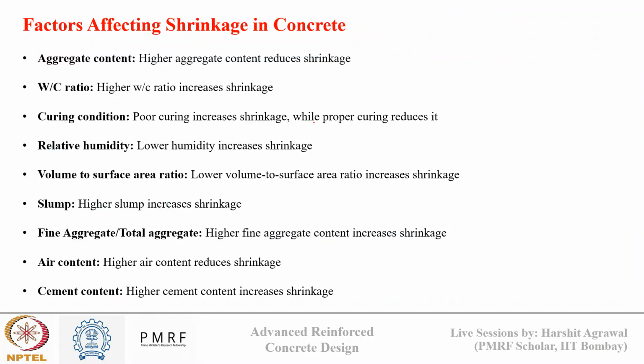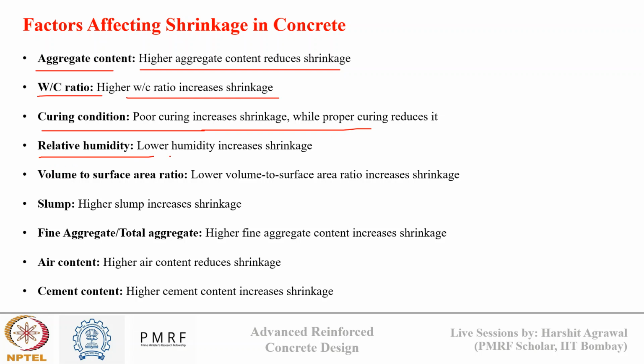Okay. Now, different factors can affect shrinkage in concrete. Aggregate content: these will be similar to what we talked about in creep. The higher the aggregate proportion, the lower the shrinkage, because it gives stiffness to the concrete. If the W/C ratio is higher, there will be more shrinkage. If curing is not done properly, there are chances of water evaporation, then shrinkage will rise. If there is low humidity, there will be more moisture evaporation, and more shrinkage. The higher the surface area of concrete, the more surface is available for moisture loss, so more shrinkage. Higher slump means there is more water in the system, so more shrinkage.